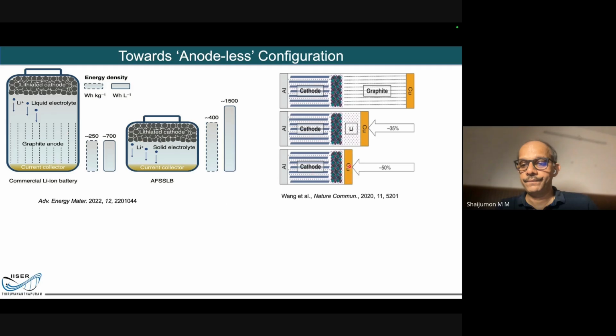That's what we call a very revolutionary concept, called the anodeless configuration. I put it in quotes because the terminology is not great from a pure electrochemistry point of view, because there is nothing like a device that can exist without an anode. The idea is that the anode is limited, because if I were to keep a lithium metal there, I don't need that very thick lithium. In this concept, the cathode is lithiated because it's lithium cobalt oxide. It contains lithium. So I start with just a copper foil there, with no other material. The lithium from the cathode will come and deposit onto this copper layer, and in situ it forms an anode of lithium.